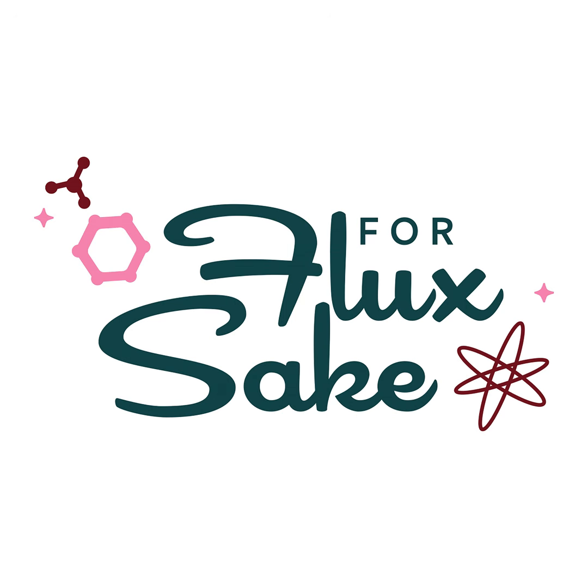So that's the first major stage of the firing. The second stage is 67 degrees C, 120 degrees F to 1222 C or 2232 F. Okay. Medium heating rate, if you look at it, is 60 degrees C per hour. So they're slightly going past that medium heating rate, but we'll just call that good because they're using the Fahrenheit concepts, and Fahrenheit is 108. They go to 120. Why? I don't know. Make it nice and round, whatever.